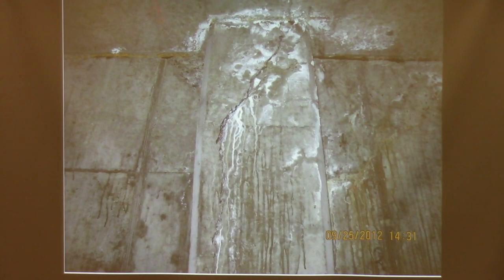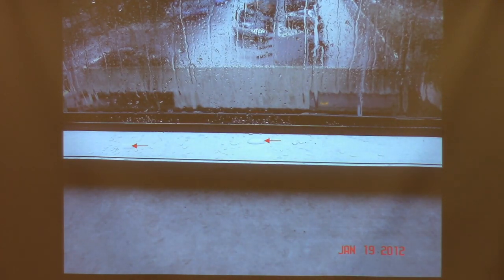You see cracks in the pilaster. And you go inside, and over time, this thing had been thoroughly looked at by a lot of different people, but you see cracks in the shear walls, and there hadn't been any earthquakes, there hadn't been any big winds. Why do I have things that really look like they're structural cracks? It's a little odd. Well, we'll take a little look at that. This is some of the issues that came out because of all the post-tensioning that were in these systems.